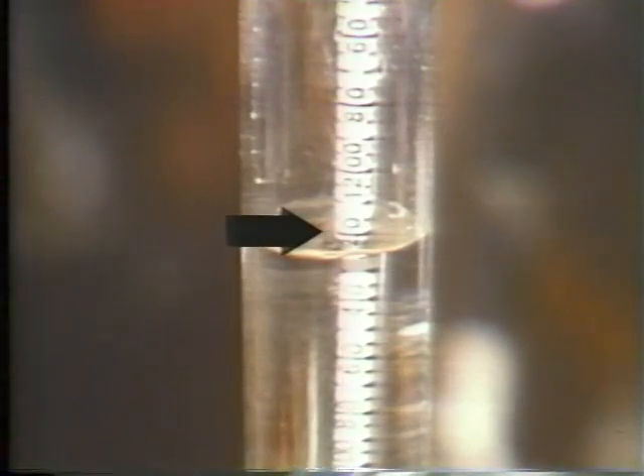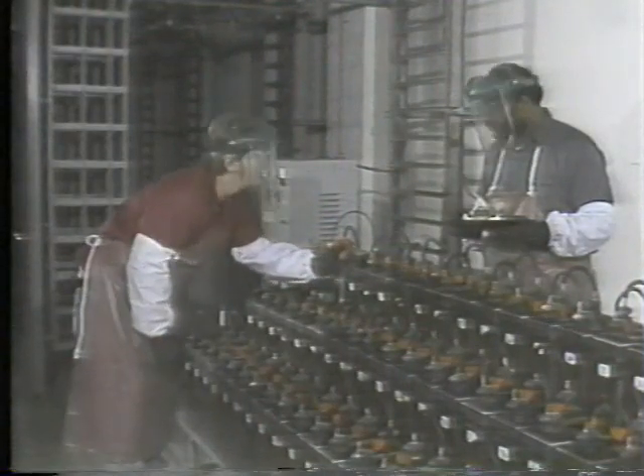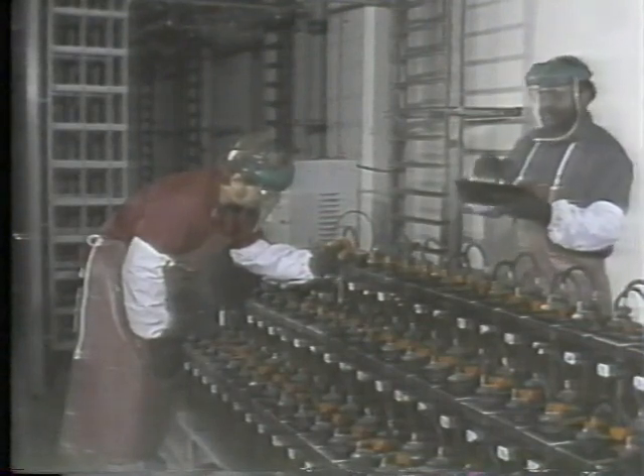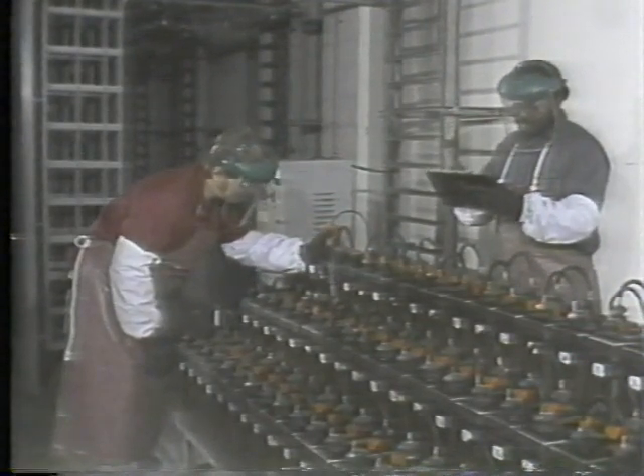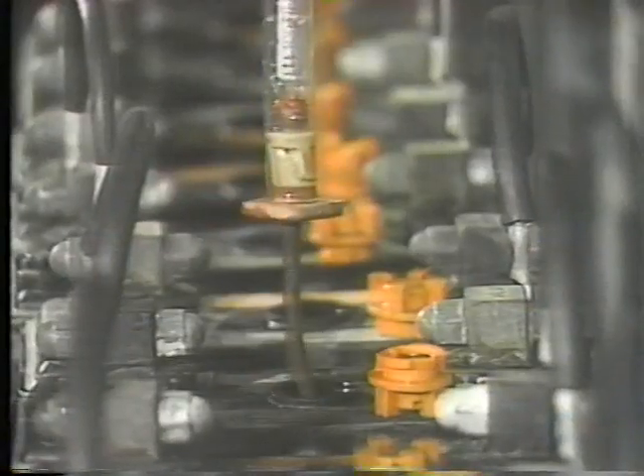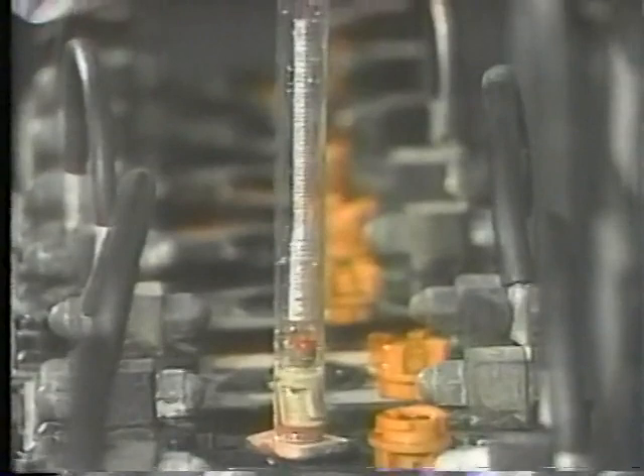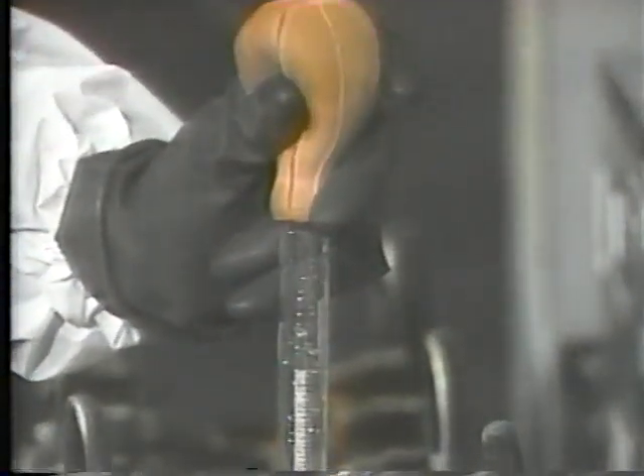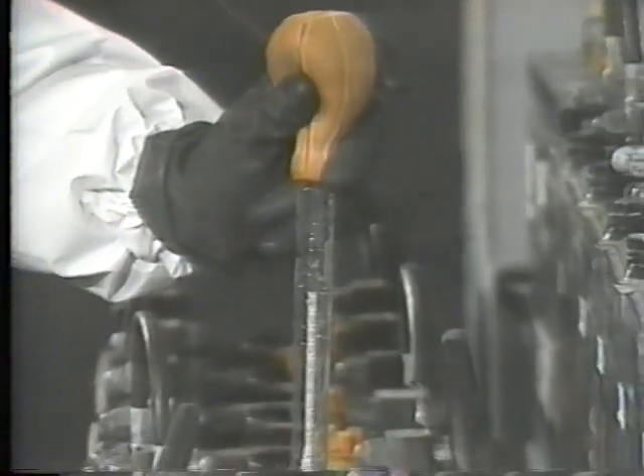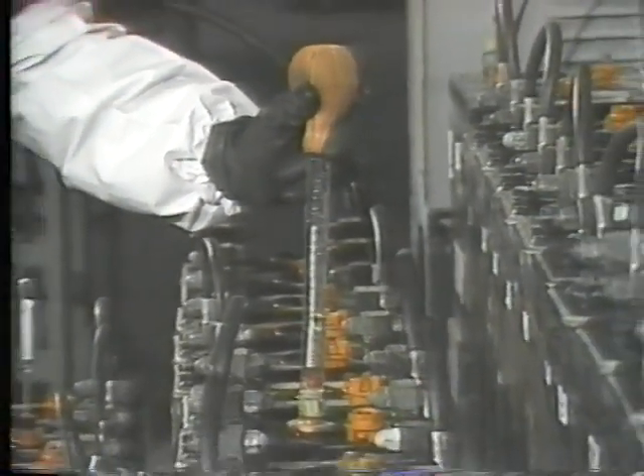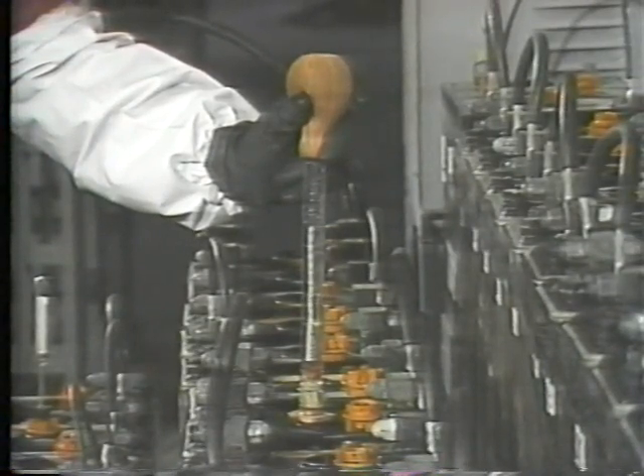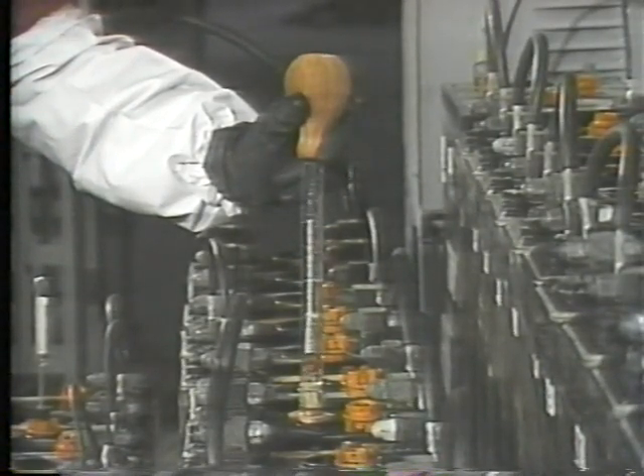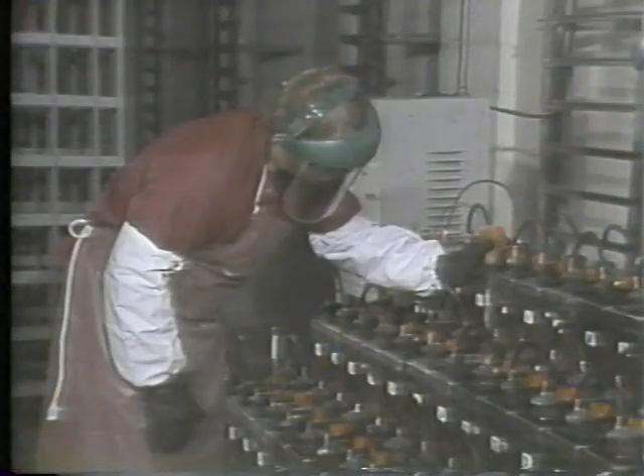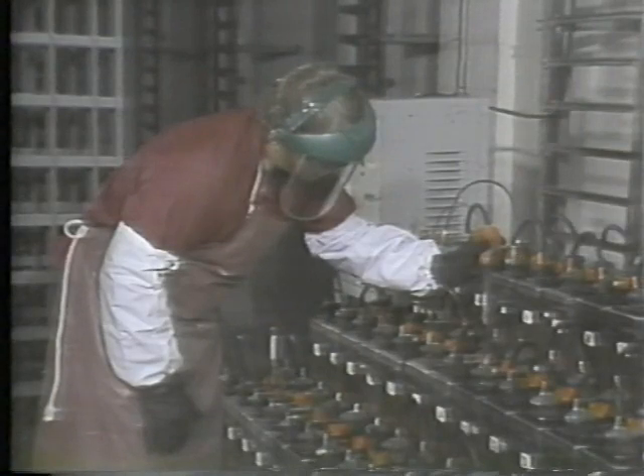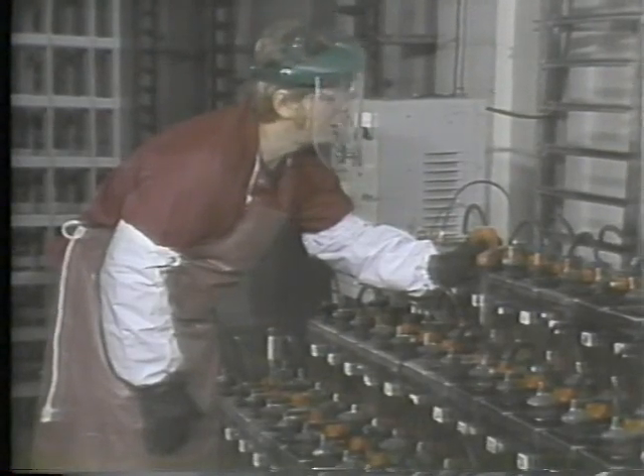This cell reads about 1220, or 1.220. After taking the measurement and recording it, squeeze the bulb again and return the electrolyte to the cell. Then move on to the next cell and repeat the procedure. To get the most accurate specific gravity measurements, two considerations have to be taken into account. First, hydrometer tests shouldn't be done right after watering the battery. It's best to charge a battery for a specific period of time after adding water. This allows the water to thoroughly mix with the electrolyte. Otherwise, the water will just sit on top of the denser sulfuric acid solution, giving you a false reading.